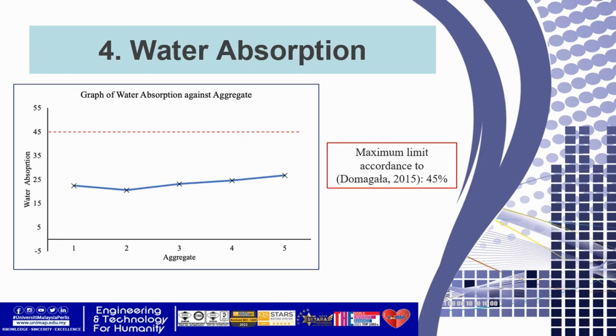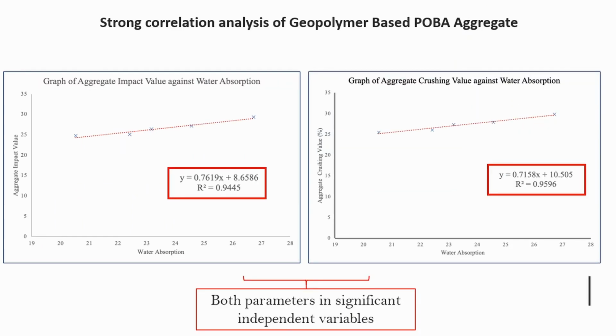And for the water absorption, you can see that all samples show water absorption in the range of 25%, which is still under the limitation. And here is the graph of the aggregate impact value versus water absorption, and also the graph of the aggregate crushing value against the water absorption. As you can see here, both graphs show a strong correlation between the aggregate impact value or aggregate crushing value against the water absorption.